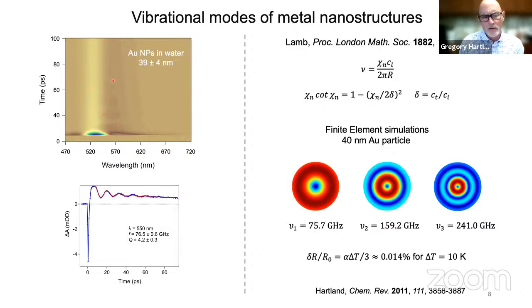You see them in the transient absorption spectrum because as you have this breathing motion, the particles change size a little bit. So there's a change in the electron density, and that change in the electron density moves the plasmon band back and forth a little bit. And that gives you the signal in the transient absorption experiment. If we look at the signal at a single wavelength, this one's at 550 nanometers, you can see these oscillations that are the breathing mode. You can fit that to a cosine to get both the frequency and the damping time. And we usually express the damping times in terms of a quality factor, which is essentially the lifetime divided by the period. Okay, so this sample has a quality factor of about 4.